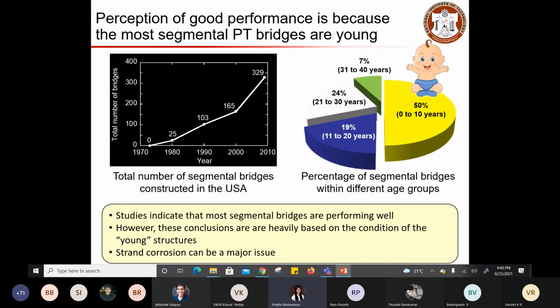So again here, strand corrosion becomes the major issue, and this is even more severe compared to your conventional reinforced concrete. I'll tell you why in the coming slides. Because when you have pre-stress, the strands are already under stress. So in that case, that has high energy to react. So the corrosion potential is higher in such type of steel reinforcement that we use. So the chloride threshold value will be lesser for pre-tension concrete systems.